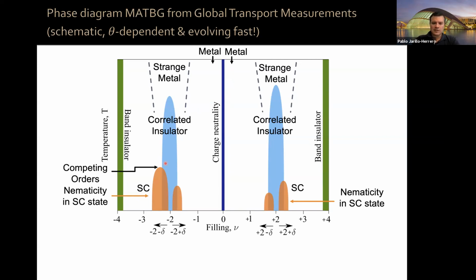We also saw that near the top of the dome, we have competition between different orders, which tend to suppress superconductivity in certain regions. We also found that there is nematicity, so a breaking of rotational symmetry, in the normal state of the system. Okay, so I'm going to be telling you about all this today.